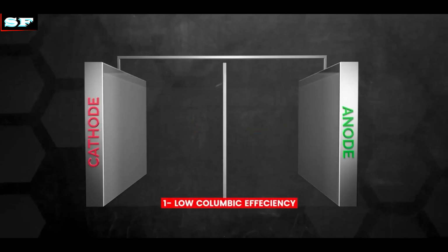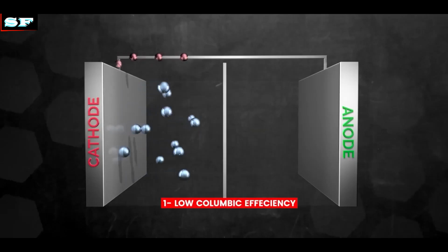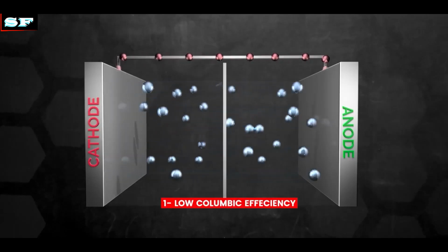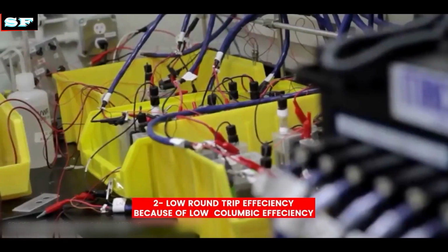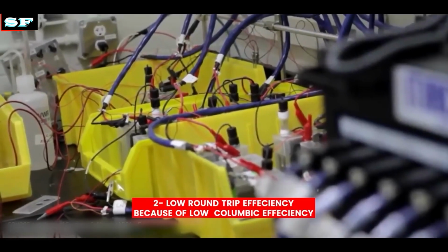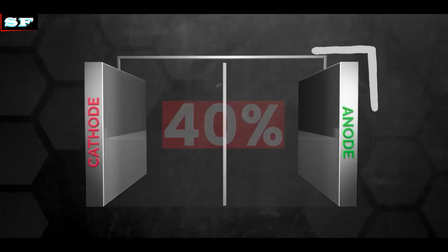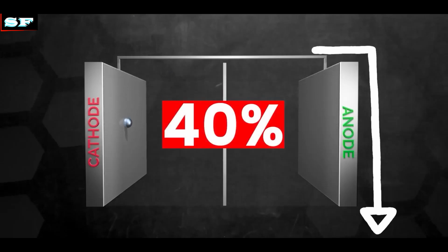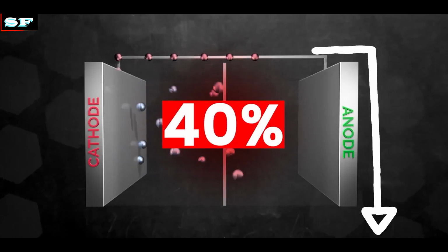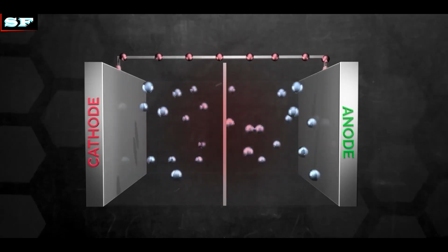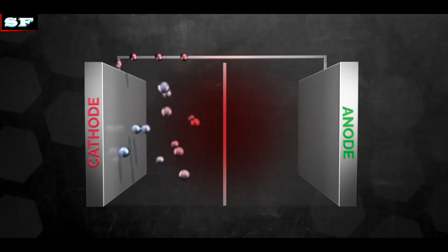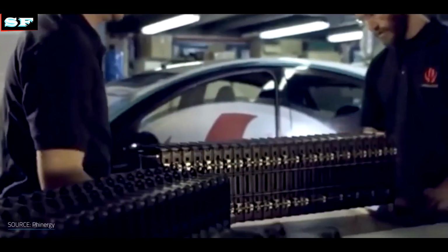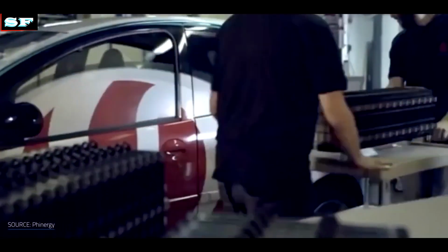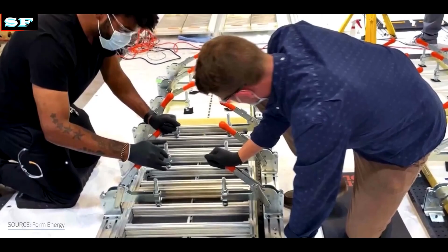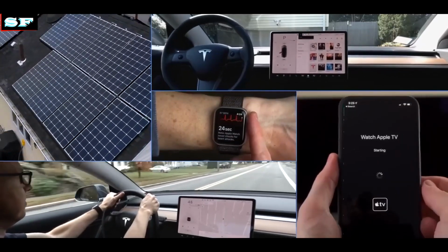First, they have low Coulombic efficiency due to the undesired hydrogen evolution reaction that competes with the desired reduction of iron during charging. Second, they have a low round-trip efficiency of around 40% due to this low Coulombic efficiency and a high overpotential during the charging and discharging cycle. This means a significant amount of the energy required to charge an iron-air battery is lost and not available during the discharge of the battery, reducing the amount of energy that is stored.